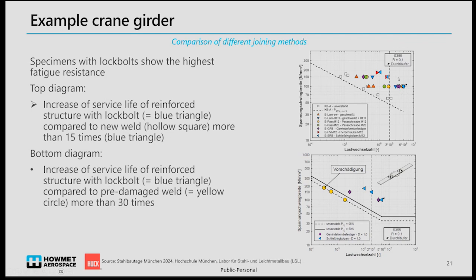In this case, the lockbolts and also a thread forming fastener were used for further investigations using a pre-stressed specimen, which was then reinforced with this repair method. And in comparison to the damaged welded structure, an increase of the remaining fatigue life of more than 30 times that of the damaged structure could be achieved using Lockbolts. So here we can see a very good result in a typical application.